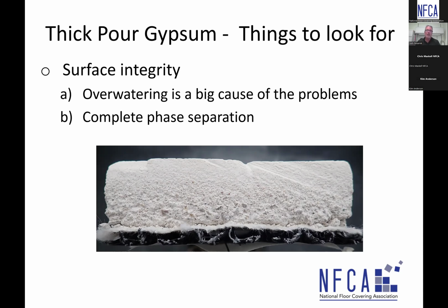And phase separation is what we're seeing in this picture, where all the heavy materials like the sand fall to the bottom and all the lighter materials float to the top. And we're left with a very weak surface. This is a cross section of a thick pour gypsum that was, quite frankly, simply overwatered. And the sand aggregate fell out of suspension. It's down at the bottom, and you have no aggregate at the top, and you have a really weak surface.